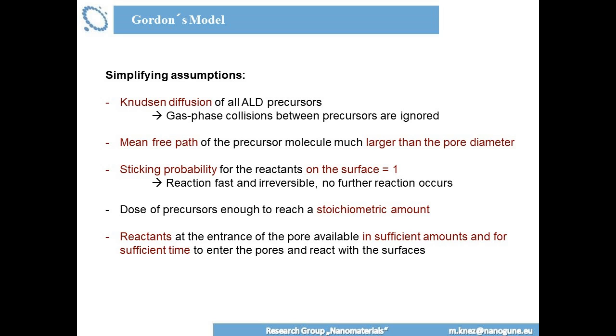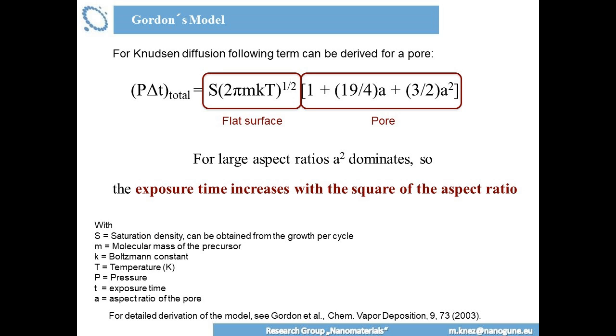Now, if you start from those assumptions, according to Gordon's model, you will end up with such a formula. And this formula tells you that the time for exposure, given the pressure of the molecule, the partial pressure that you use, contains two factors. One of them is related to the flat surface, but you have the other one, which is related to the pore. And if you have a pore with a higher aspect ratio, this term here prevails.